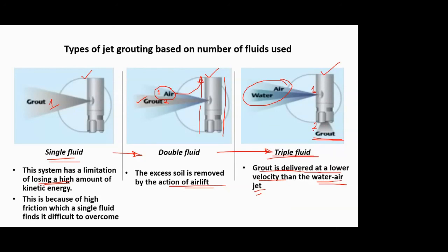One more thing to take care of: this grout should not be too fluid or too workable, because we are already introducing water into our system. We can't remove this water, otherwise it would become a grouting plus dewatering technique. So we'll not do anything for this water; we'll keep it as it is. You can reduce the water content in the grout itself, so that it gets mixed with this water and then solidifies later. Only the air we can expel by airlift. All right, so this is about jet grouting.